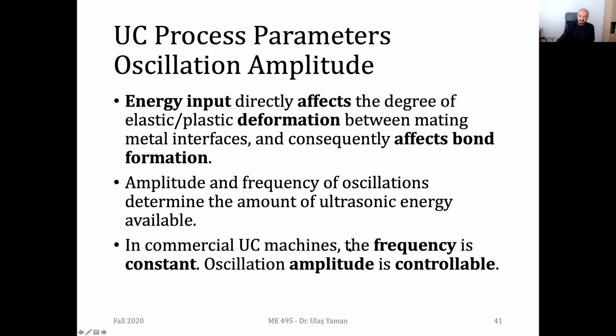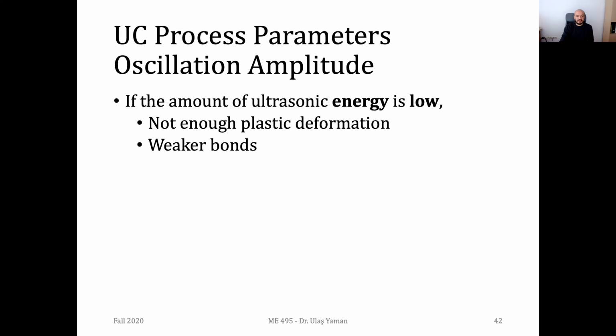Since the frequency is constant, mostly equal to 20 kilohertz, we can assume it as a constant value. So if the frequency is constant, we can only play with the amplitude of the oscillations to adjust the amount of energy we are applying on the parts. This is the only thing we can play with in terms of ultrasonic energy. Depending on the material you are using, you may have higher or lower amplitudes. If it's a soft metal, then with low amplitude oscillations you can do the joining. But if it's a difficult material, then you need to increase your ultrasonic energy by increasing the amplitude of your oscillations.